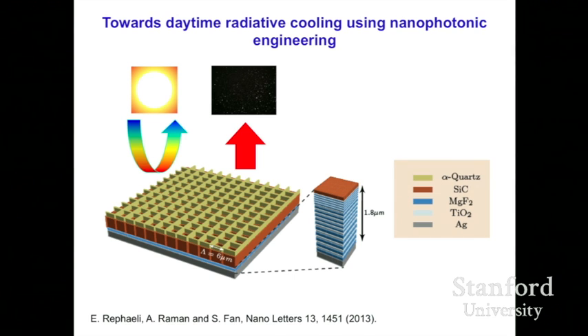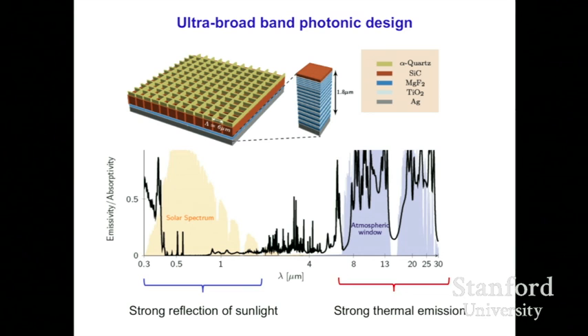Now, these materials have lattice vibration. For example, in the silicon dioxide, you have vibration between the silicon atom and the oxygen atom. And the resonant frequency of those oscillations happens to be around the thermal radiation frequency. So consequently, they have strong thermal radiation, and putting a grating or a periodic structure on top further enhances such thermal radiation. So combining these structures or materials together, you can get an emissivity profile that looks like this, having very low emissivity in the solar spectral range and high emissivity in the thermal radiation wavelength range. So this satisfies the theoretical condition that we talked about for radiative cooling.